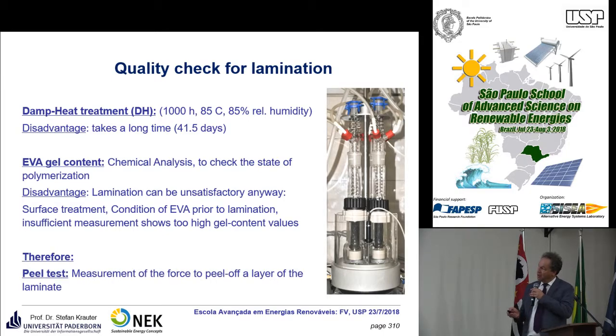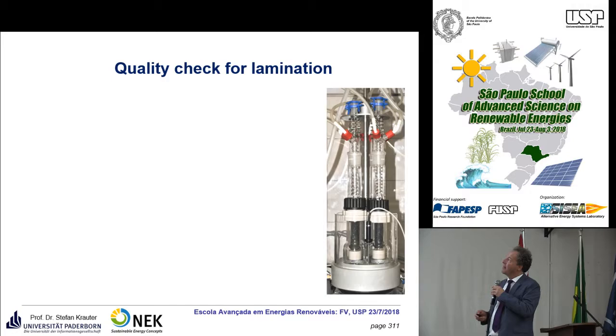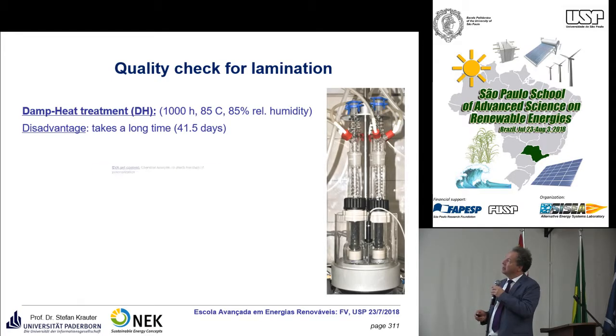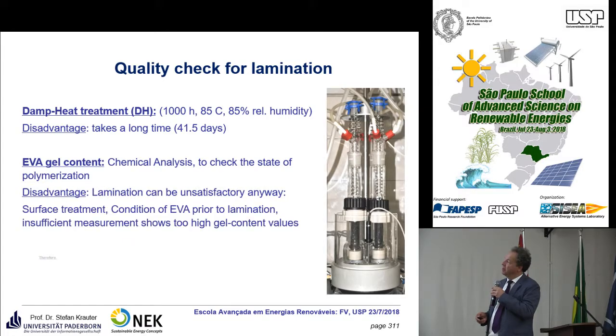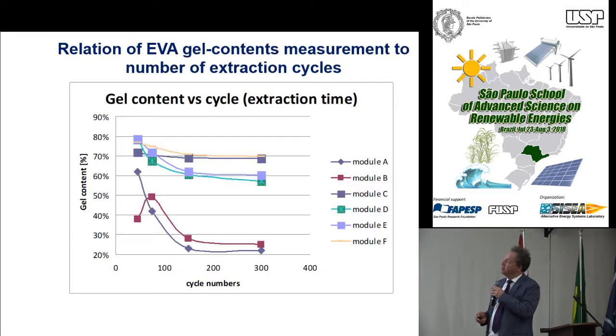So therefore, we could use a peel test. We measure the force to peel off a layer of the laminate. So we peel off the layer and we do a gel content test.